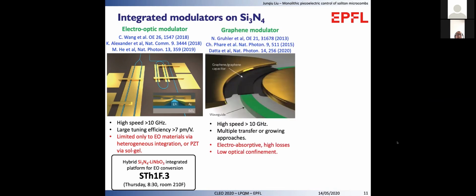The second scheme relies on graphene modulators. This scheme also has high speed, above 10 GHz. The graphene layer can be grown or transferred to silicon nitride photonic integrated circuits via multiple schemes. The disadvantages are, first, the modulation is electro-absorptive, so the loss of the device is modulated. It requires weak optical confinement such that part of the optical mode interacts with the graphene layers.